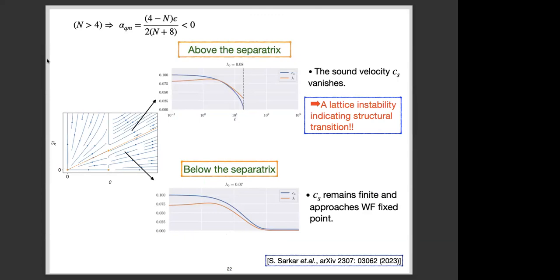Okay, let's see what is happening in this regime and in this regime. So to see that, for now let's imagine we are here above the separatrix and we plot the sound velocity CS. It's not quite clear, but the blue curve basically gives you the sound velocity, and we plot it with the RG scale, and the orange line is basically the elastic constant. So what we see is that in this regime, the sound velocity actually vanishes after a finite RG scale. So this goes to 0, but the elastic coupling remains finite. So the sound velocity vanishes, and this indeed basically dictates that there is a lattice instability in this regime